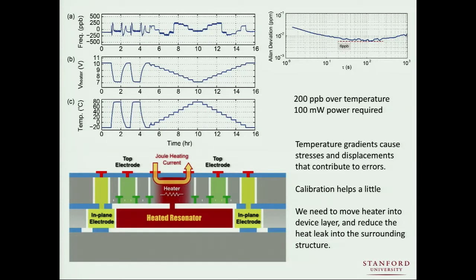It took about 100 milliwatts of heat because we're dumping the heat into the cap, and there's a lot of thermal contact that allows that heat to spread. That creates a huge temperature gradient in the cap, which pushes a lot of the electrodes and contacts around and causes other problems. And what we really learned coming out of this is we've got to move the heater down into the device layer. If we use cap heat or die heat, we're causing all kinds of problems that are just in the way.